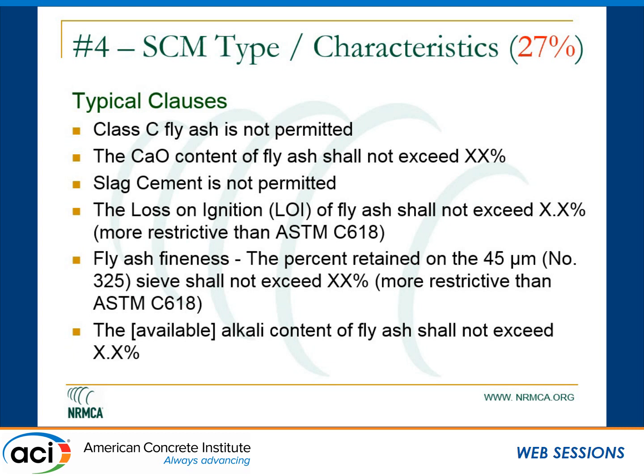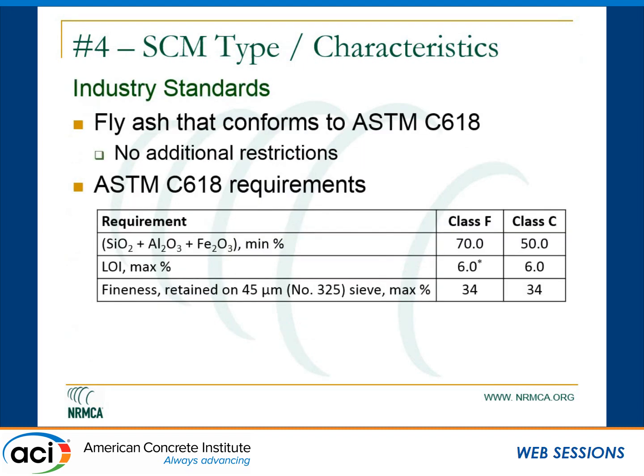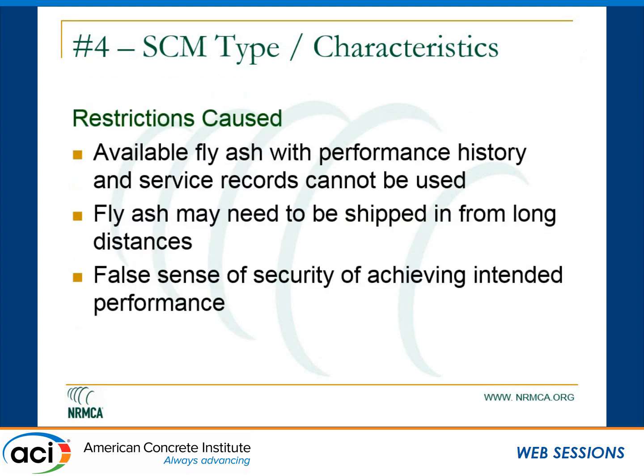The other one that we see is that the available source of fly ash, which is now getting to be a problem, is restricted from use because of additional restrictions within a specification, such as not permitting the use of Class C ash or changing the loss on ignition requirements, that basically say that available supply cannot be used. And that's one of the problems. There are no specific restrictions within our industry standards on the specific fly ash other than it meets ASTM C618. The thing is that producers develop a history and comfort with the particular materials that they use, and if they're forced to use something else, they don't have that history.